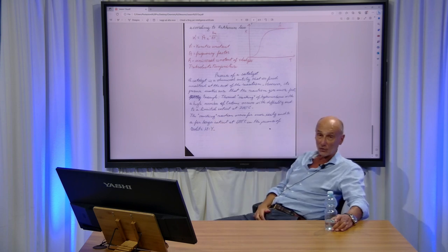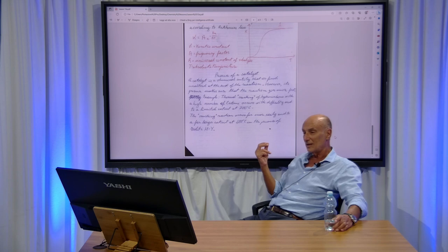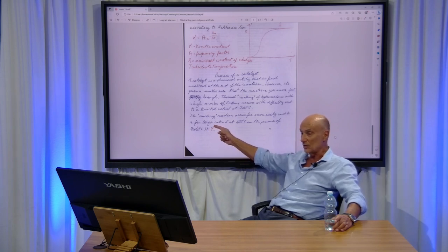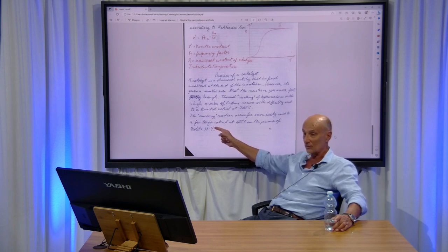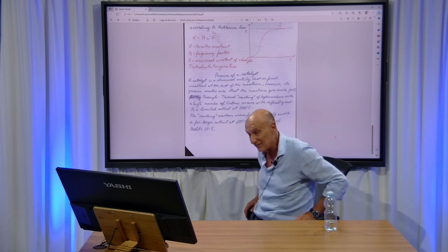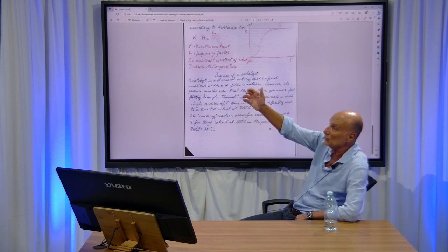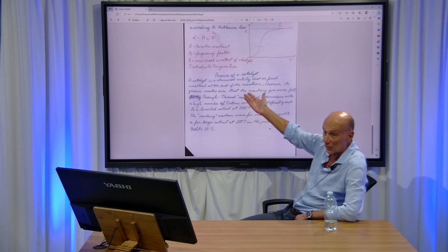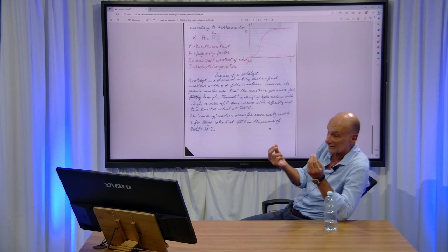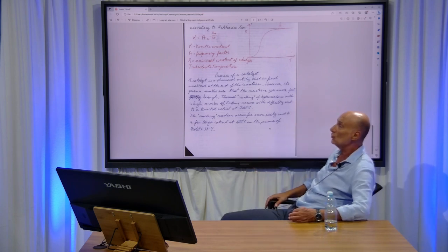Y in its hydrogen ionic form. These zeolites exhibit a lot of active sites in which there are electron holes, namely a hydrogen atom that is bound to the network of SiO2 atoms of the zeolite Y does not have any electron, so it has an electron hole. So these active sites are very eager for electrons, and they take this electron from the sigma bond existing between the various carbon atoms of the hydrocarbon molecules. So these carbon-carbon bonds are made much weaker by this attraction of the electron hole of the zeolite HY, and so this reaction occurs far more easily.